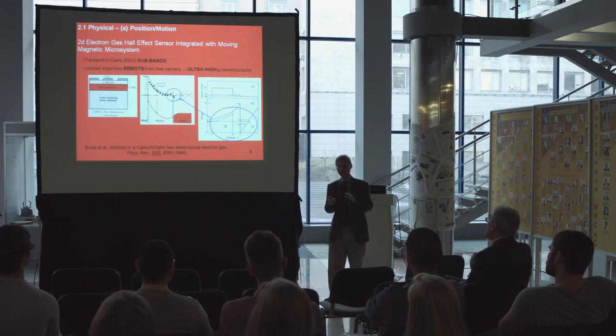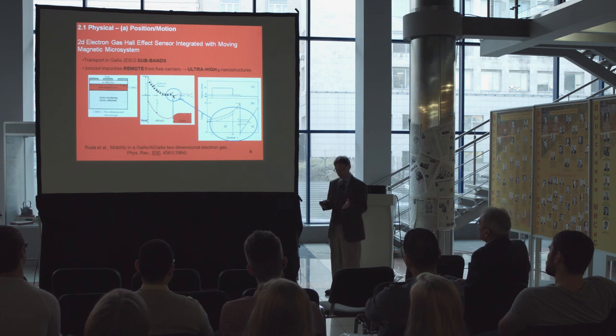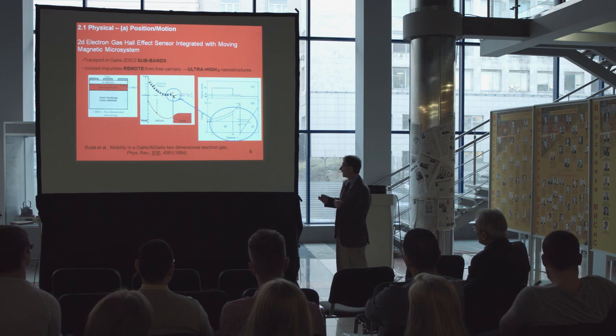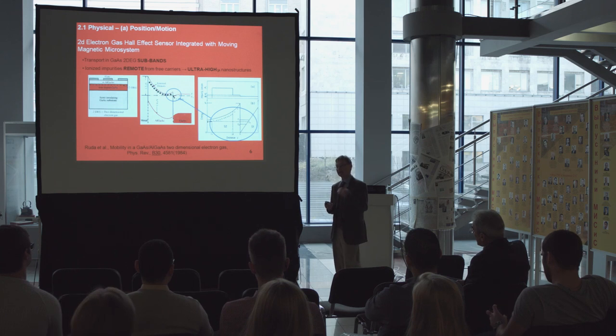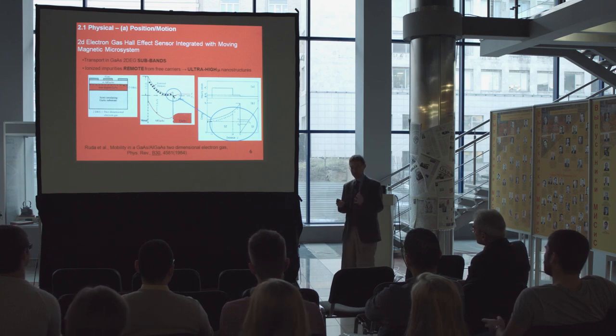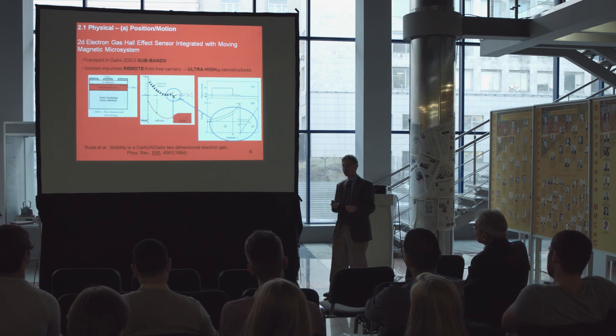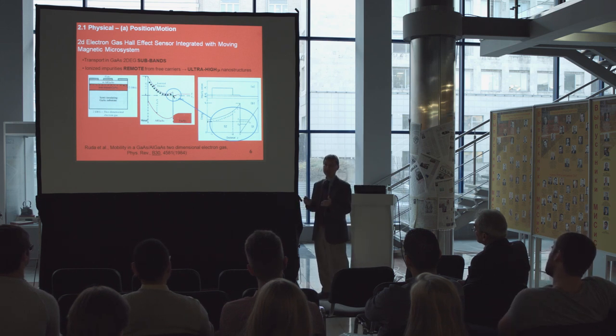Because if you think about a bulk material, what makes a nanostructure here and what makes it a bulk material? So apart from the quantization, what's important is in a bulk material, in order for me to get the carriers that sit in this thing, these black carriers, I have to ionize the donors. But the carriers only move so far from the donors. So the donors, which are charges, are a background to the carriers around them. So the scattering efficiency by a Coulomb center, which is what it is, is very, very high. So the mobility is low.